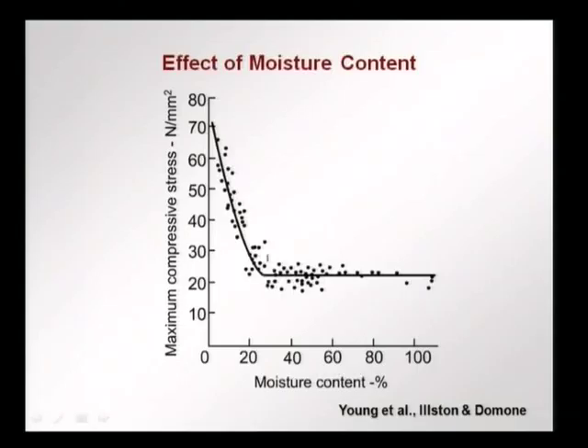Then we reach the fiber saturation moisture content, fiber saturation point, and if we continue to decrease moisture even beyond this, now this is about 25 to 30%, then we find that now the cell walls are drying, there is compaction of the cell walls, the molecular chains are coming closer together, there is better hydrogen bonding, and therefore the material strength increases. So, if we decrease the moisture content much below the fiber saturation point, we have an increase in strength, and this is what we want.